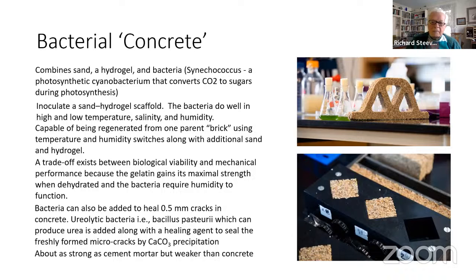And what also is interesting about this is I mentioned several times that concrete in general develops cracks, and I'm pretty sure this is being done now, where some of this is being mixed in with concrete, and it will heal small cracks in concrete so as to prevent them from leaking, or allowing water to enter the concrete, get at the steel and corrode the steel that provides a lot of strength to the concrete.